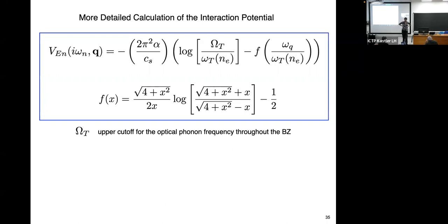The story with Gor'kov-Melik-Barkhudarov is that you have a prefactor of Fermi energy, and anything at energies larger than the Fermi energy can be incorporated into the normalization of the interaction, the scattering amplitude. That's right, which you don't do. You deal with whatever interaction you have. So the question is: don't you restrict yourself to pairing very near the Fermi surface, putting EF as an upper cutoff, in a situation where EF is small and you may have pairing extending far away from the Fermi surface, which will give you larger TC because then you will involve fermions not necessarily on the Fermi surface?